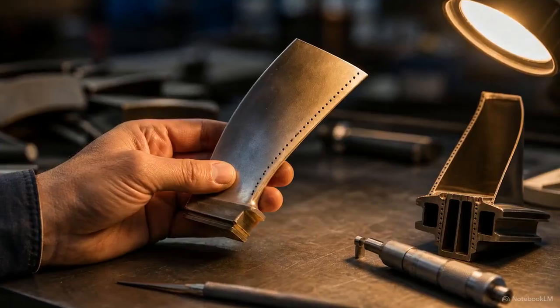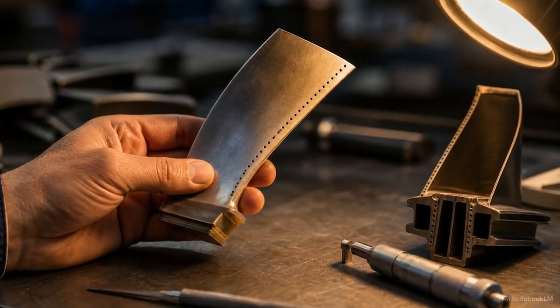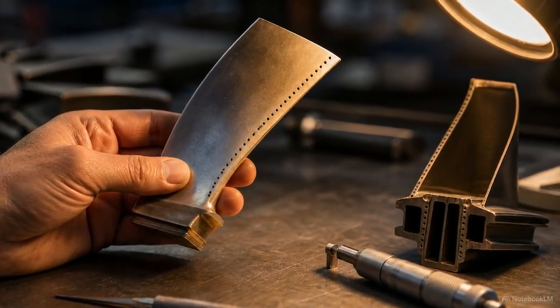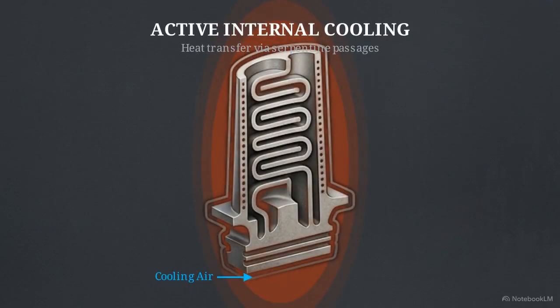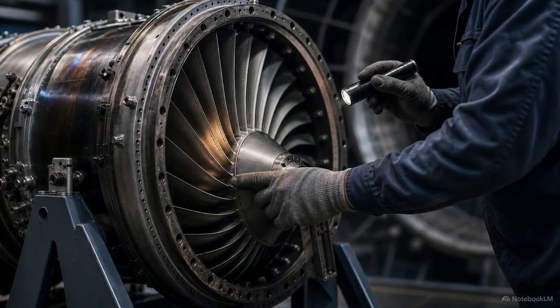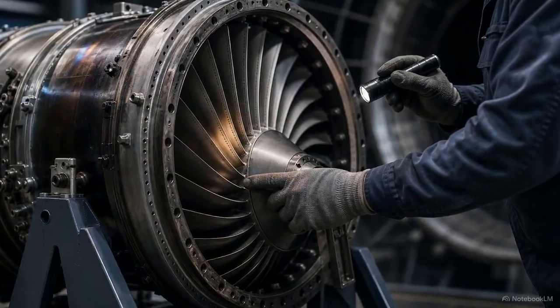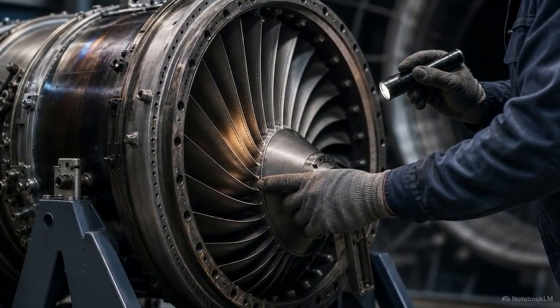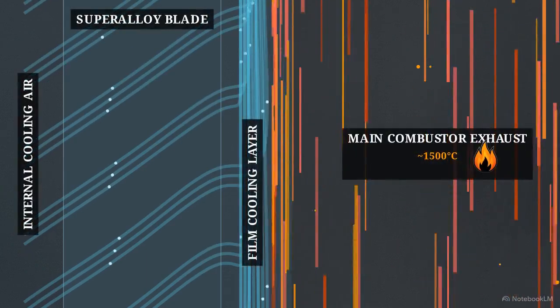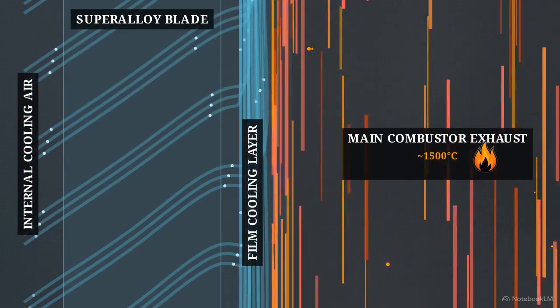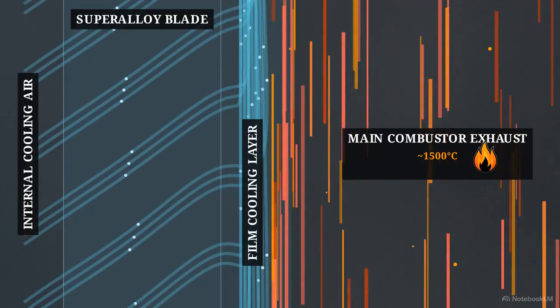The second layer of defense is active internal cooling. The turbine blades are heavily hollowed out to allow airflow. High-pressure air is bled off from the compressor and routed into the base of the blade. It moves through an intricate internal maze of serpentine passages to draw heat out of the metal. That cooling air is then forced outward through tiny holes drilled into the blade's surface. This creates a process called film cooling. As the air exits, it sweeps over the outside of the blade, creating a boundary layer of cooler gas that insulates the metal from the main combustor exhaust.